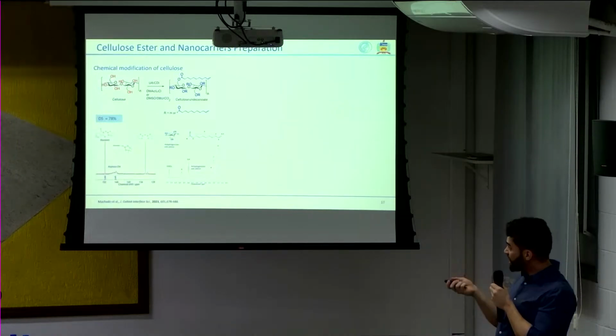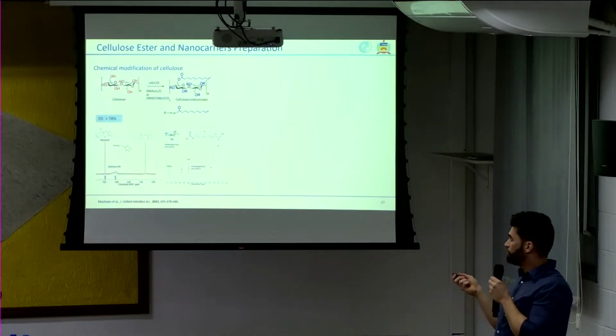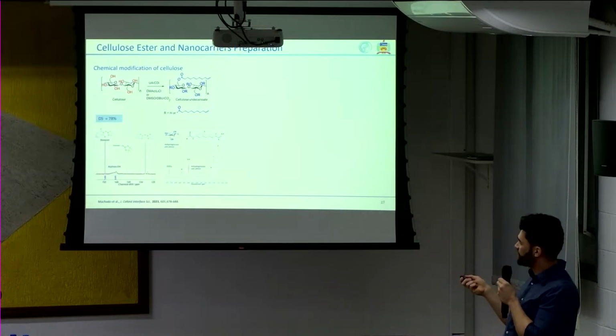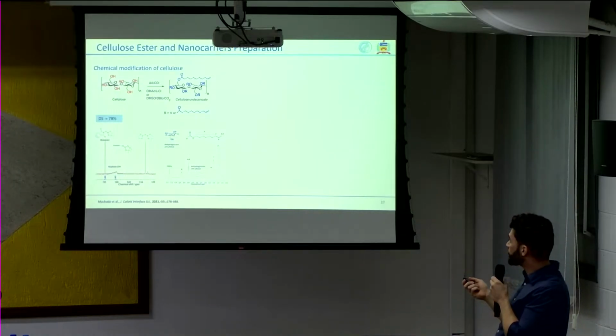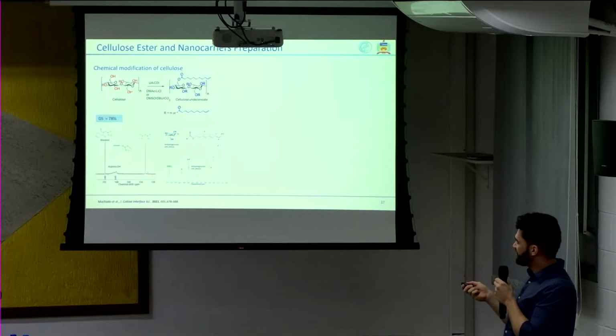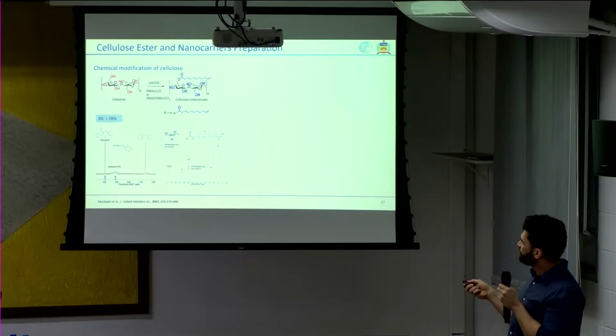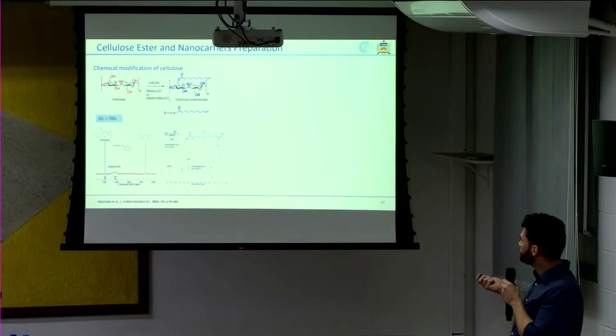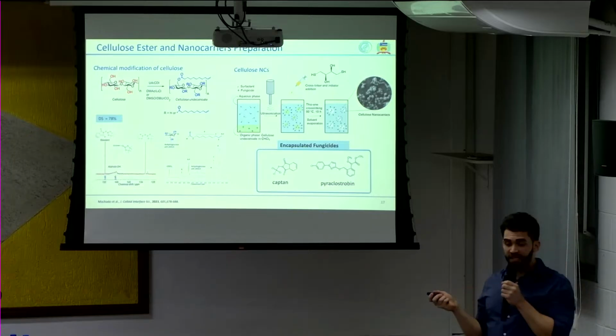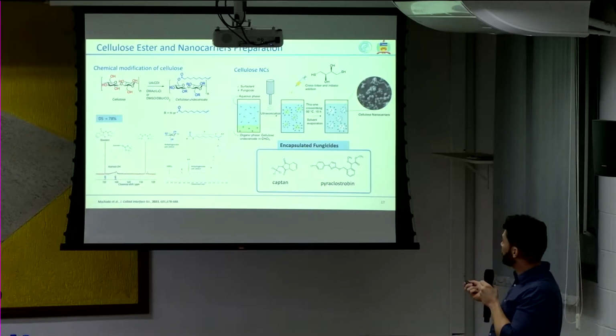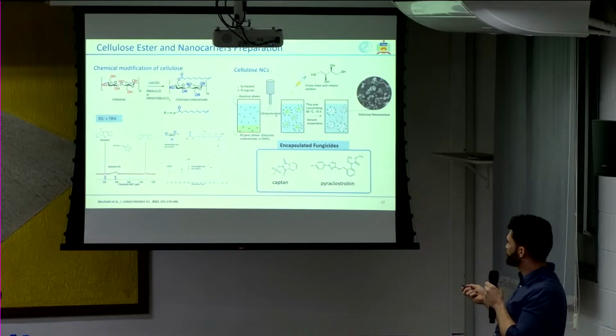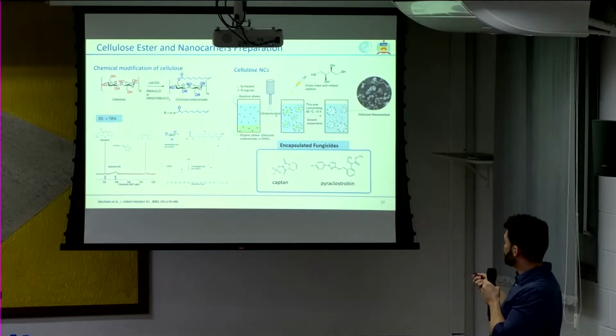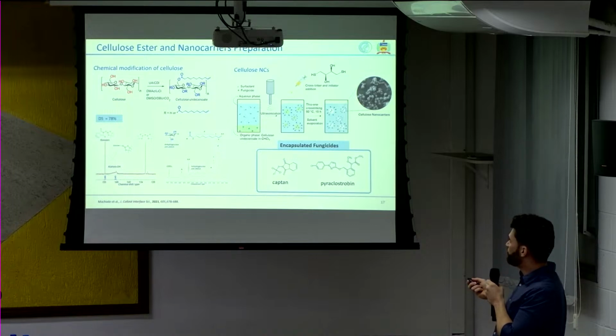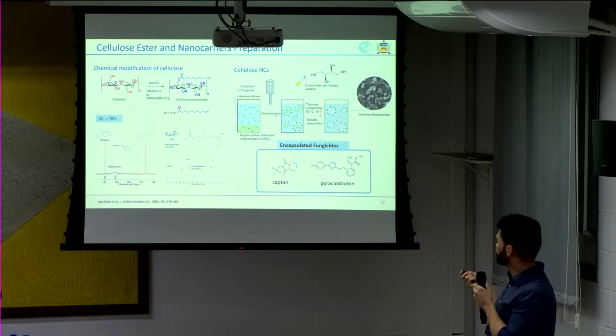And for cellulose, methacrylation of cellulose was a little bit complicated, so we used a fatty acid instead, undecenoic acid that we've used before in the previous work. And we did an esterification, so we got 78% of degree of substitution, so 2.3 out of the 3 hydroxyls per unit was esterified. Also, we calculated it by NMR. And the cellulose nanocarriers were synthesized using miniemulsion polymerization as well, in a similar system where the encapsulated fungicides were added to the organic phase. And here we use thiol polymerization because this double bond is not reactive for Michael addition. So we use free radical thiol.